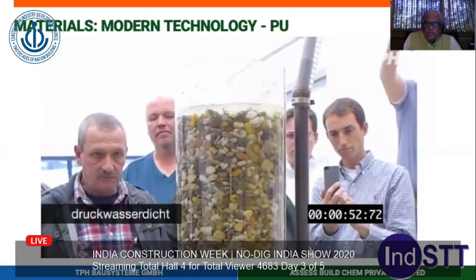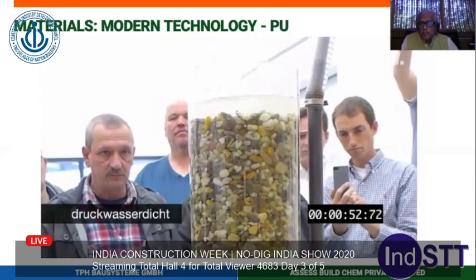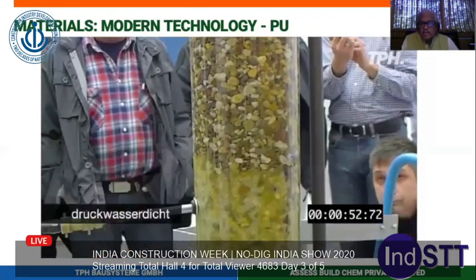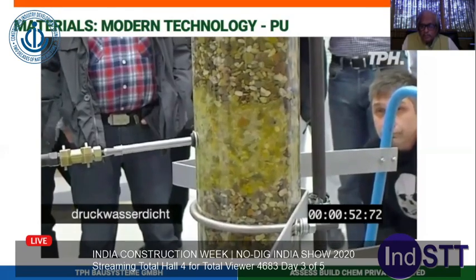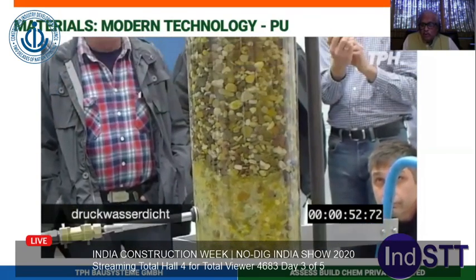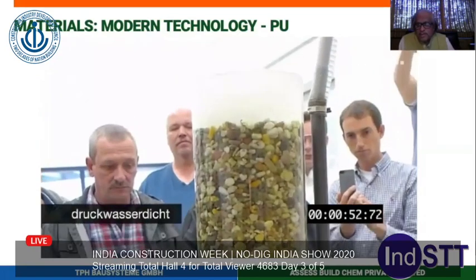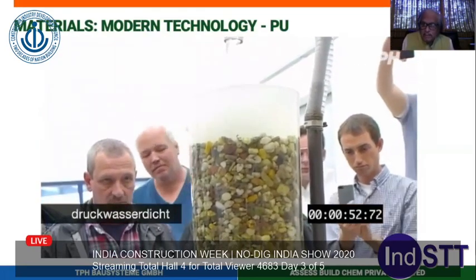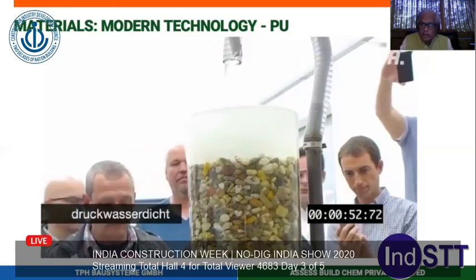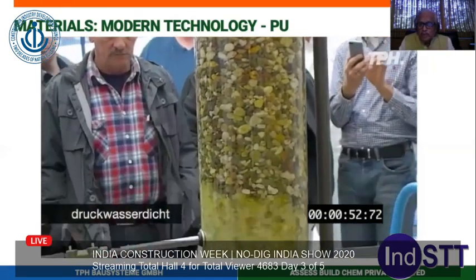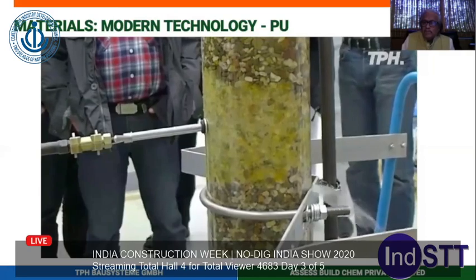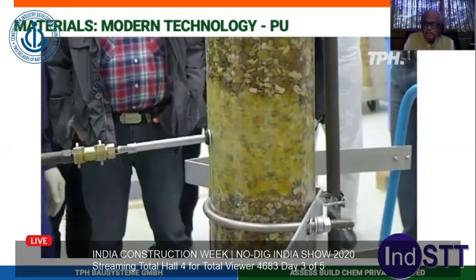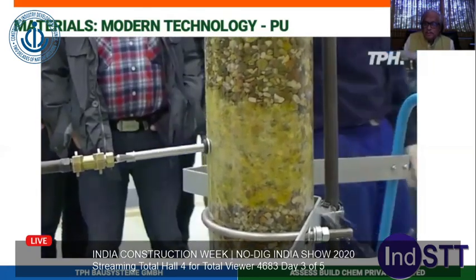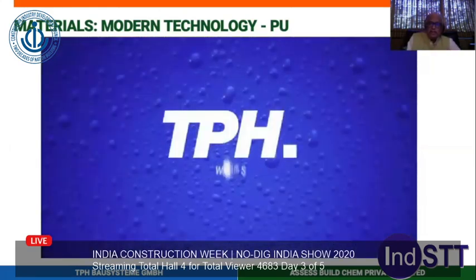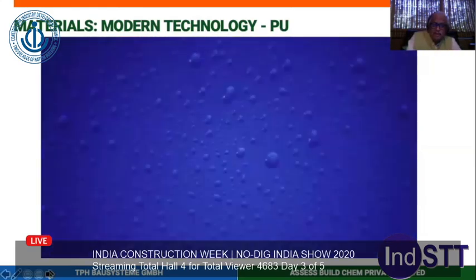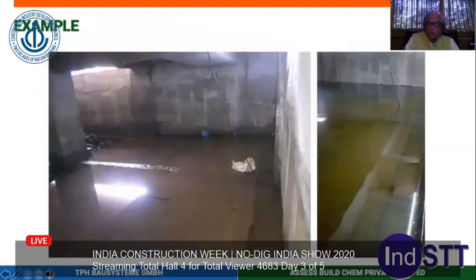If you see now, the water has stopped going inside and the water is rising. If you see from the bottom, the stream of water is getting reduced. It has expanded, not very much, but to a reasonable extent so that it is spread all around. The water from the top is flowing out. The water which is coming out with gushes is now slowly stopping. And within a matter of 1 minute, the total process is over.